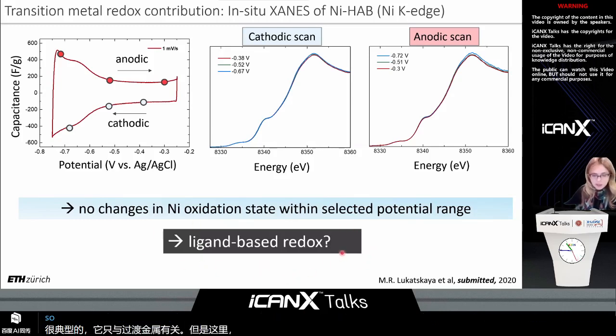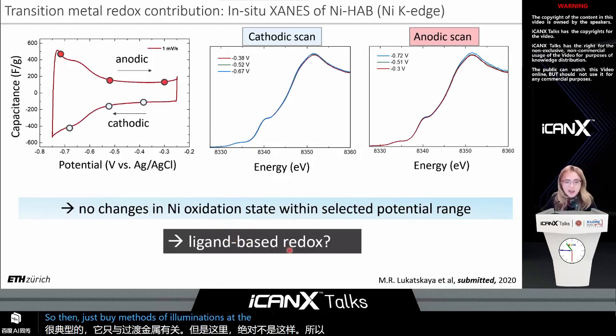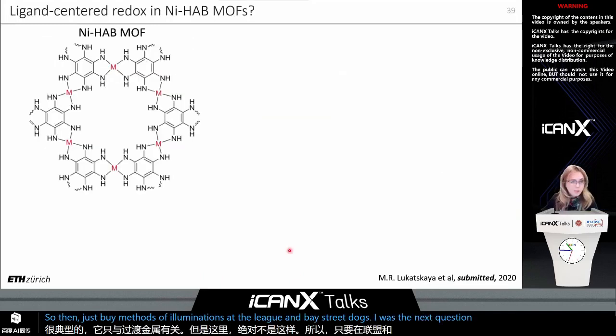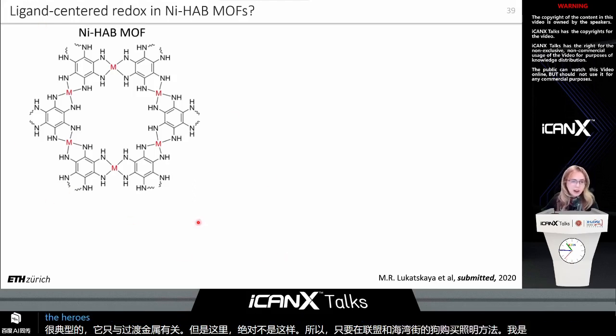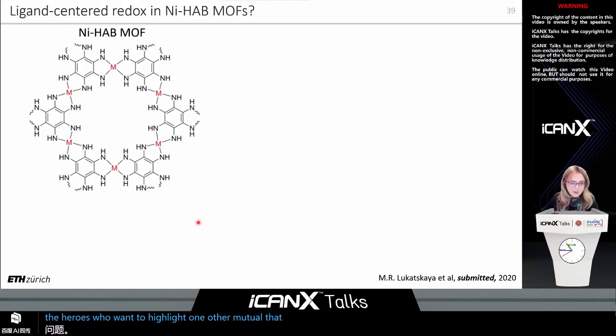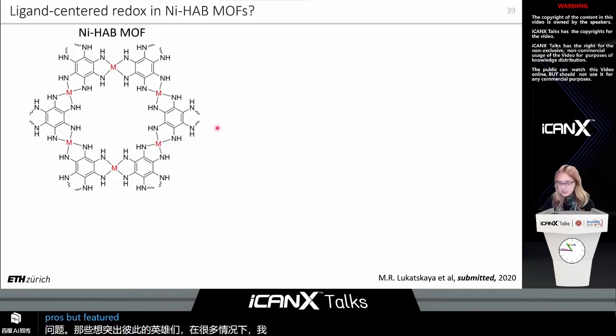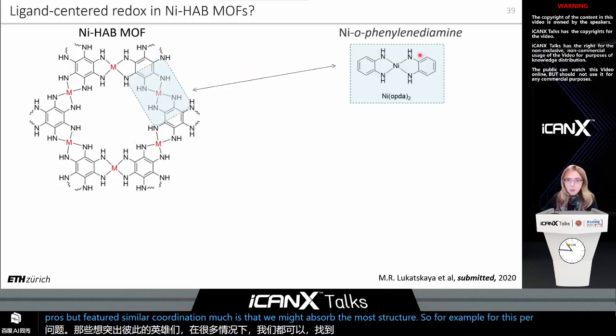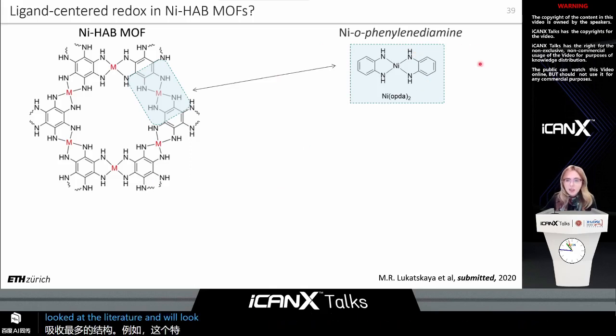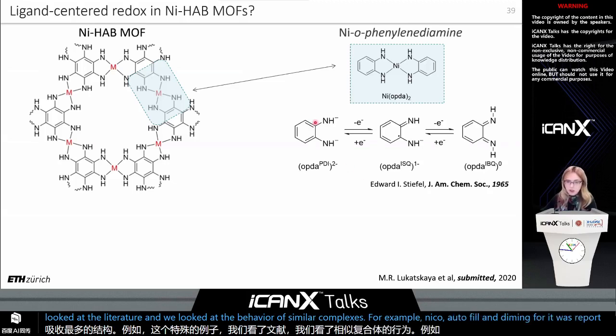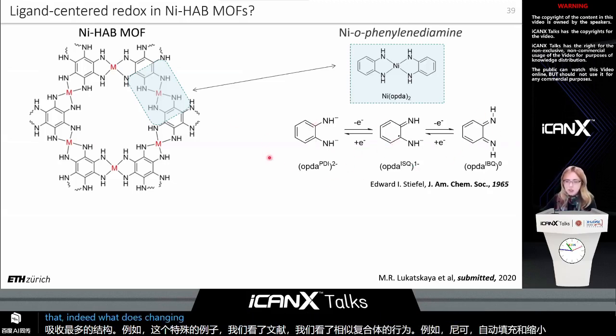So then, just by method of elimination, is it a ligand-based redox was the next question that we wanted to explore. And here I also want to highlight one other beauty of MOFs, that in many cases we can find model compounds which are not porous but feature similar coordination motifs that we might observe in the MOF structure. So for example, in this particular case, we looked at the literature and we looked at the behavior of similar non-porous complexes, for example nickel o-phenylenediamine, for which it was reported that indeed what is changing the oxidation state is the ligand, not the transition metal.